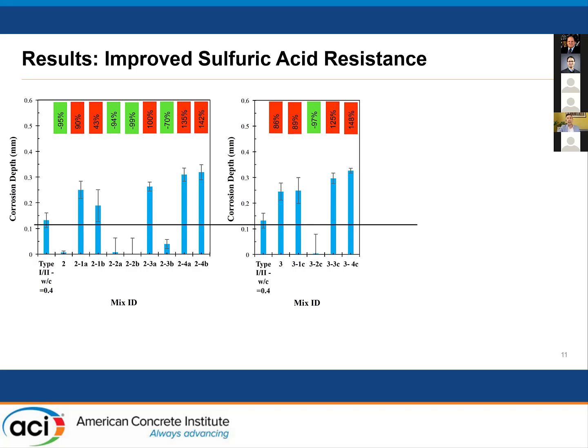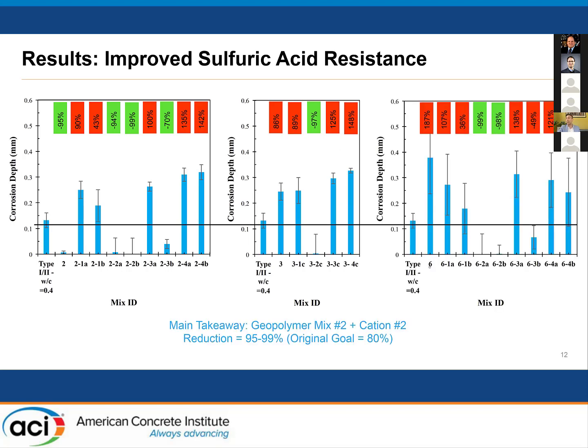And again, mystery cation number 2 was the best performer, whereas the other cations did not show enhanced sulfuric acid resistance. And then the same was true with the original geopolymer mix number 6, where again, cation number 2 prevailed. So really the main takeaway for us up to this point was that geopolymer formulation number 2 with cation number 2 is our winning formulation compared to our OPC benchmarks.